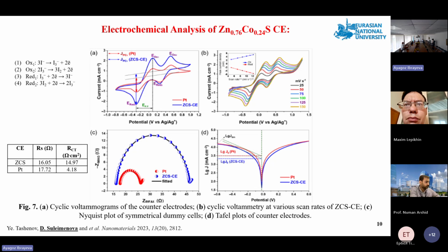EIS analysis in symmetrical dummy cells shows that zinc cobalt sulfide has slightly lower series resistance than platinum, meaning excellent adhesion and contact behavior between the FTO substrate and counter electrode, but much higher charge transfer resistance, which indicates increased internal resistance at the counter electrode electrolyte interface, and the reduced electrocatalytic reduction of triiodide ions by the zinc cobalt sulfide counter electrode compared to the reference electrode, which ultimately affects the performance of the DSSC. Tafel results show that both materials have similar catalytic behavior and ion transfer properties, which affects the overall efficiency of the DSSC.